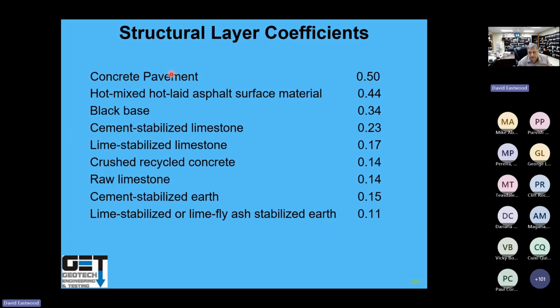The structural numbers for various materials: for concrete paving, the structural number is 0.5, which is the highest. For hot mix asphalt, 0.44. Black base, 0.34. Cement stabilized limestone base, 0.23. In this case, we have crushed stone. I'm not sure if it was cement stabilized, but for recycled concrete it is 0.14. For lime stabilized subgrade, it is 0.11.